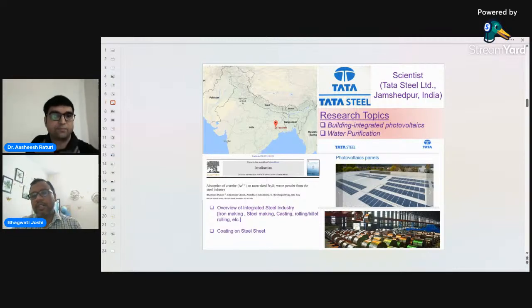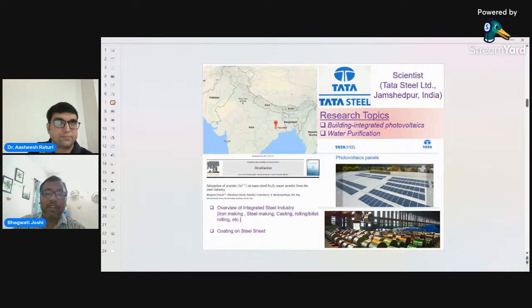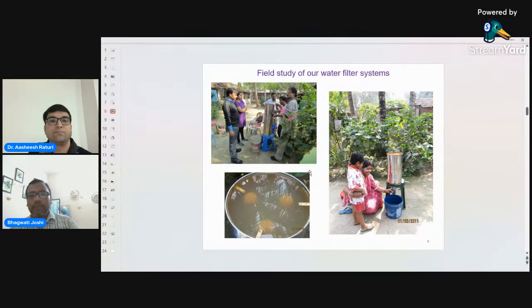What I have done is that I took those oxide fines and did some laboratory testing. I found that they are actually nano size iron oxide, Fe2O3. This is the paper that you can see we published on this. In fact, before publishing the paper, we found that these oxide fines are really useful for removing arsenic from arsenic contaminated water. We developed various water purifier filters with that, and we filed 3 to 4 patents on that. We not only developed those in the laboratory, but we really made different kinds of filters, and we installed them in the real field.